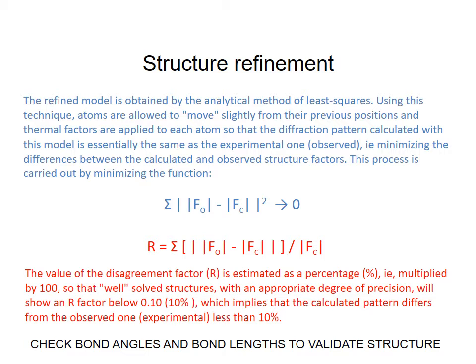This is not always the case. If that's not the case, then there must be a flaw within your crystal structure determination. For example, it could be that you have refined the crystal structure in the wrong space group. In this case, you may find that the R value is small, but your crystal structure chemically just doesn't make sense.